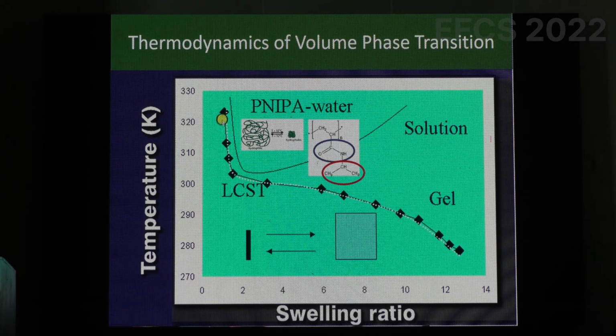and as I increase temperature, it goes in this boundary which is given by this curve here. This curve is called the binodal curve or the cloud point curve. So as I move up here, I enter into a two-phase region, and the polymer actually precipitates out. So this is an interesting polymer. Normally when you want to dissolve something, you heat up, right? You stir and then you heat up and things dissolve. This is opposite. It dissolves in water at low temperature, and as you start heating up, it actually phase separates out, it precipitates out.